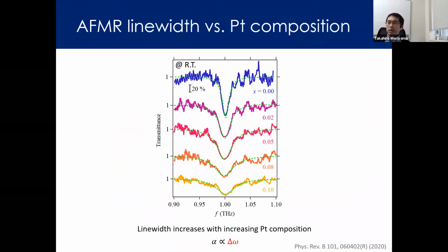So this is basically the central result of this experiment. It's the line width as a function of platinum composition. As you can see, as we increase the platinum composition, we increase the surface area, the interface area S. We see the increase of line width. Therefore, the damping constant also increases.